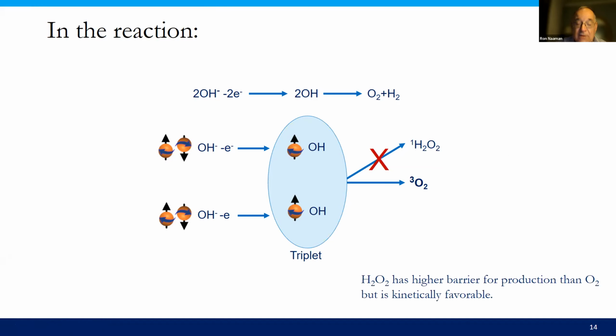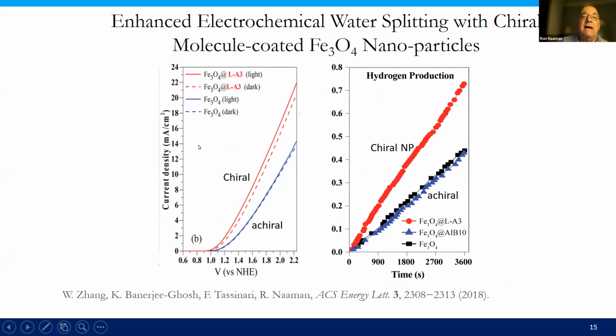So the product should be singlet, which is hydrogen peroxide, and we cannot form the oxygen. However, if we are able to control the system, if we control the spin, then we can produce OH with the same spin. That's a triplet surface. Then we produce oxygen triplet, and we don't produce hydrogen peroxide. So how do we do this? Simply we take, in this case, the catalyst iron oxide, and we coat it with chiral molecules. So you realize that we have, that's the current versus voltage, an achiral catalyst with no chiral molecules. This is the current when we coat the catalyst with chiral molecules, we get these results. Here's the hydrogen production itself, and you see it's a huge difference in hydrogen production with the chiral molecule.